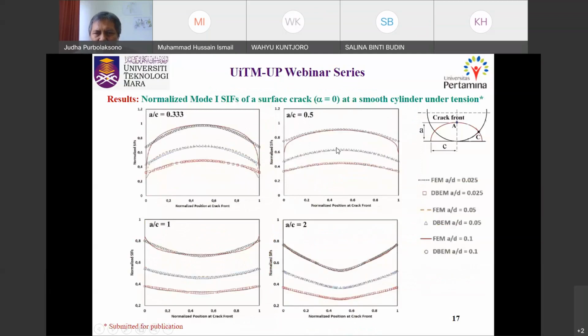Here are the normalized results, basically from the smooth cylinder for different crack aspect ratios. For example, when A over C is smaller, the pattern is going to be in a convex shape, and if it is larger, for example A over C equal to 2, then it's going to be in a concave shape like this. A over C equal to 1 still makes a concave shape, but here it is due to the effect of the corner point singularity.